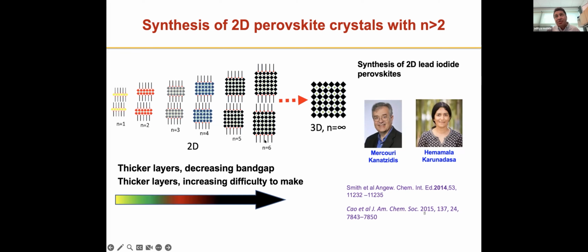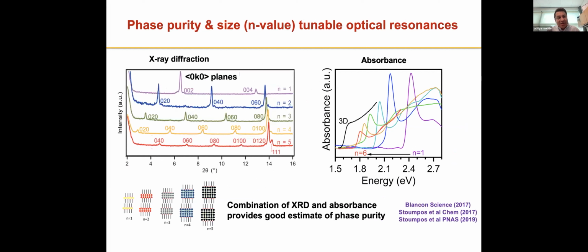And I believe now there's also N7 and N8 and N9, which become increasingly difficult to fabricate as you go to these higher N values, because the enthalpy of formation starts to become quite positive. Now, as you can also imagine, as you are increasing the number of octahedra layers, you are decreasing the quantum confinement. And so your band gap starts to get lower and lower. And as you're tending towards N equal to infinity or higher N value, which is basically like the 3D perovskite, this manifests like this.